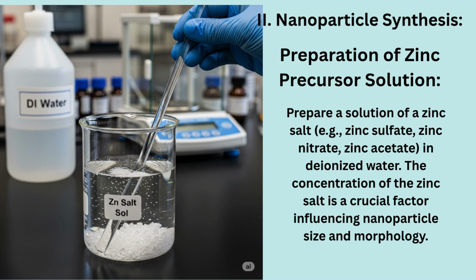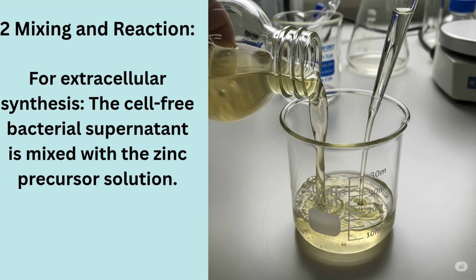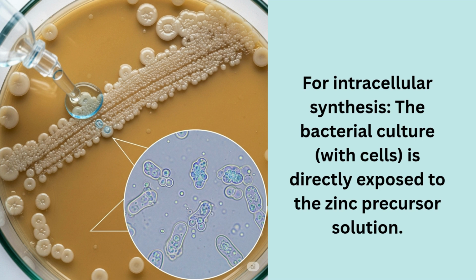2. Nanoparticle synthesis. 1. Preparation of zinc precursor solution. Prepare a solution of a zinc salt, e.g., zinc sulfate, zinc nitrate, zinc acetate, in deionized water. The concentration of the zinc salt is a crucial factor influencing nanoparticle size and morphology. 2. Mixing and reaction. For extracellular synthesis, the cell-free bacterial supernatant is mixed with the zinc precursor solution. For intracellular synthesis, the bacterial culture, with cells, is directly exposed to the zinc precursor solution.